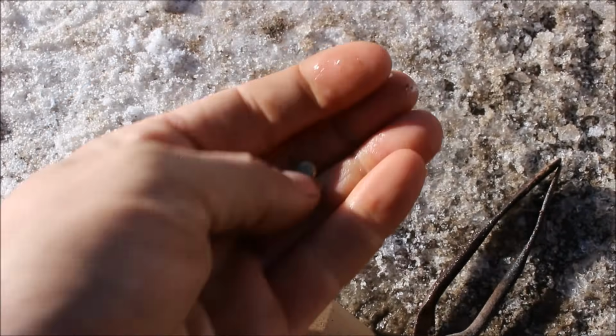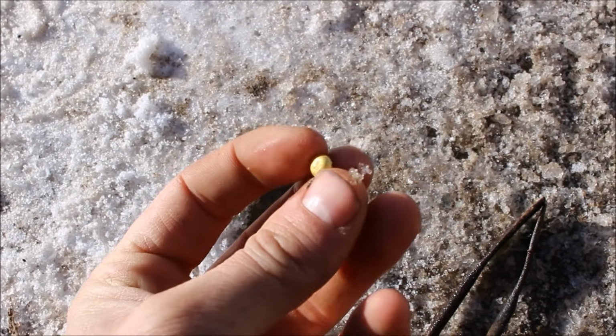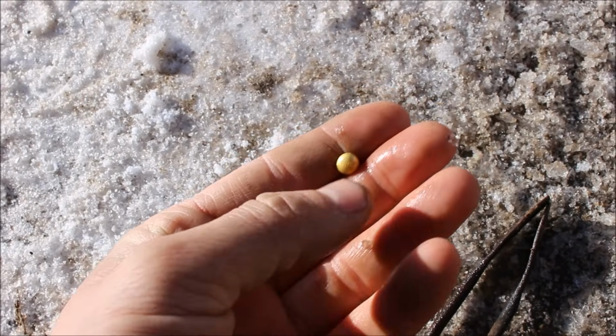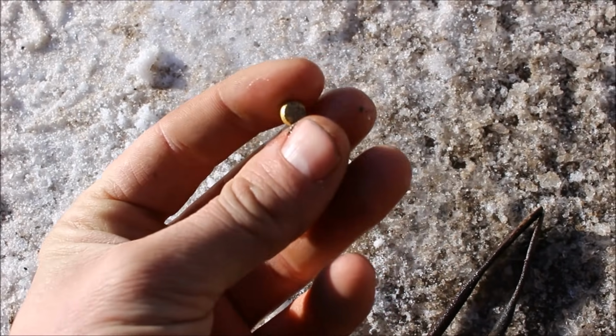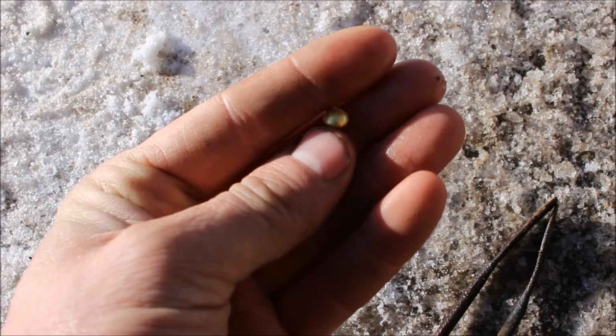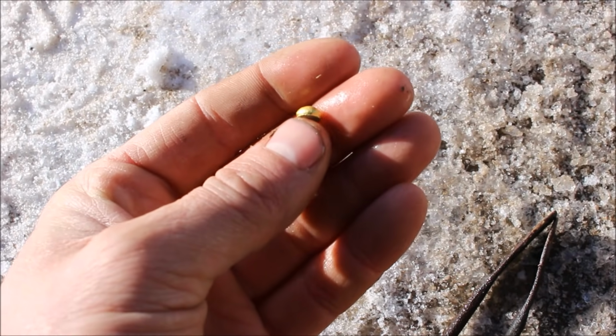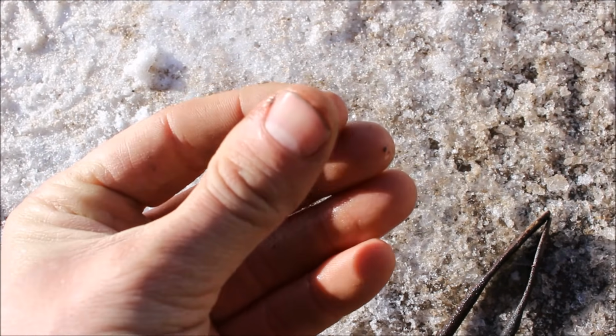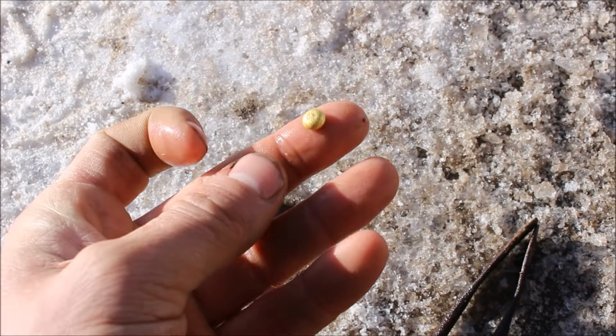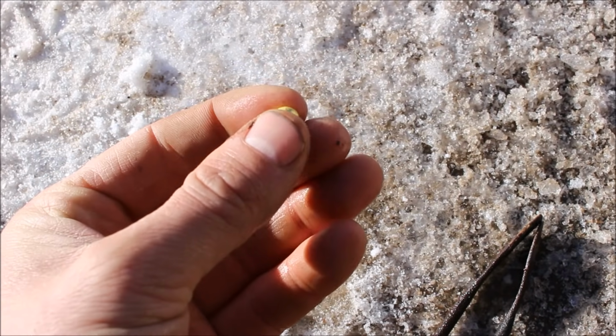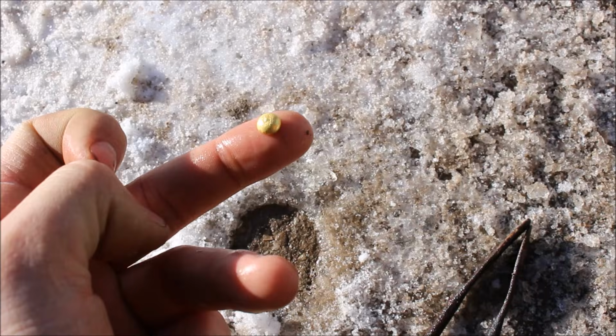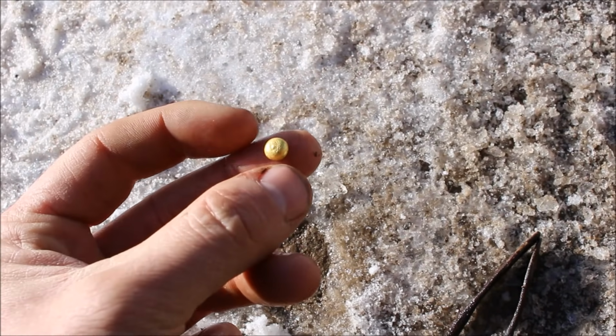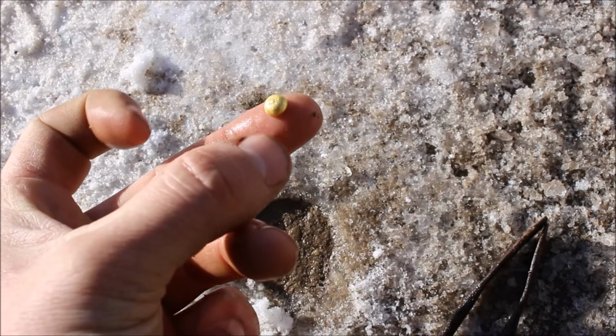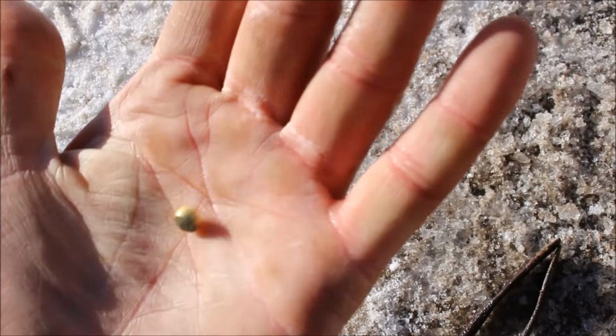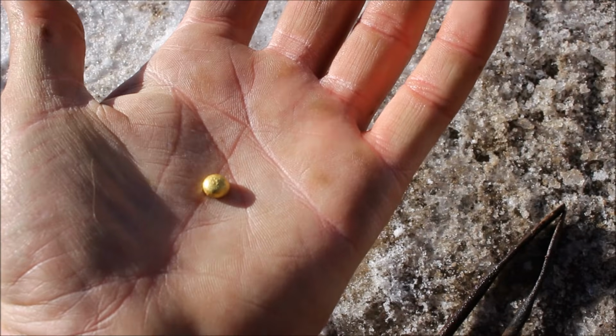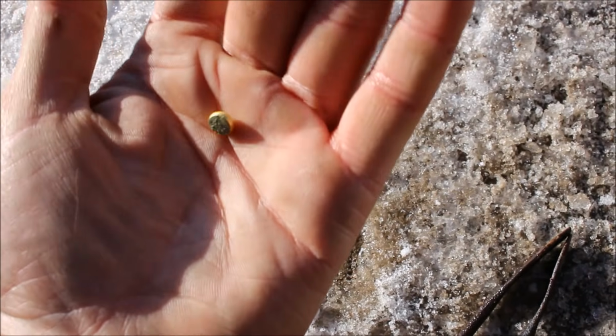Now keep in mind this is not the whole coin, because I had that piece that I cut off to use as the electrode, and this is not in here. Since that is still pure gold, I didn't want to mix it with it, because this right here is still going to need to be refined. It probably still contains maybe 0.5% of lead or so, which is enough to make it brittle and basically ruin the gold. So I need to refine this in acid before I can actually make a coin out of it. But there it is. Nice bead of gold that I extracted from those rags and recovered from my solution.